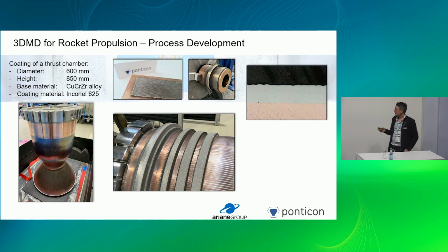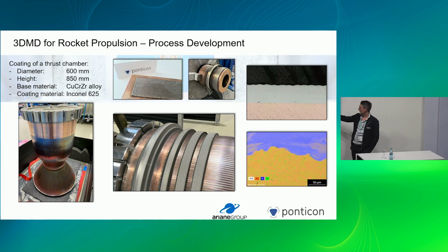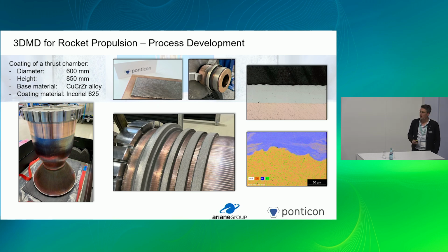Then looking at the interface, doing some cross sections, you can see there's almost no dilution. The layers we deposit have a thickness of roughly 100 micron. There's an even better image where the different elements are color coded. The orange brown is obviously the copper, the green one is the chromium, and blue is nickel. If you look at the scale down here, dilution is less than 50 micron, and there's a very sound bonding between the material we applied and the substrate, the thrust chamber itself.